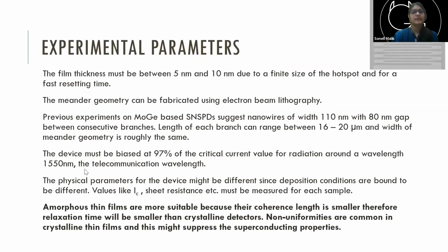Right. Experimental parameters are not important, but one thing I would like to mention is that the thin films that we make, we want them to be amorphous and not crystalline. Why we want that is because we want the heat to be dissipated very quickly. When you have these high energy electrons that arise when the Cooper pair breaks, if the coherence length is too large, it will take them longer to hit other phonons, basically the crystal, and transfer their heat down to the substrate.